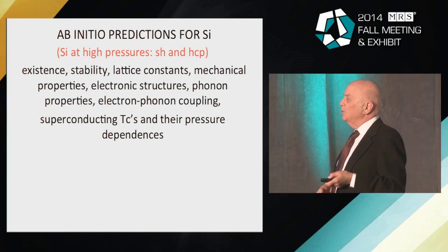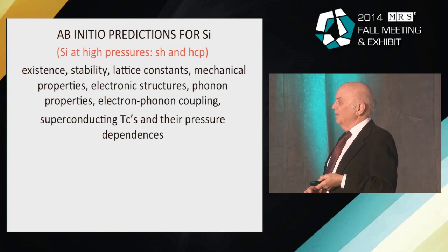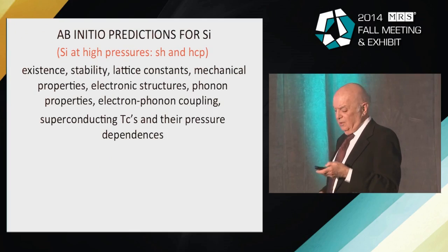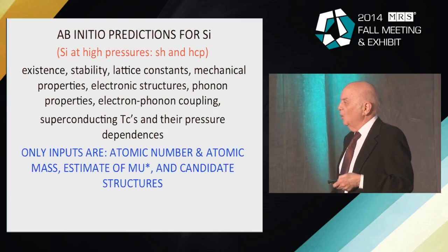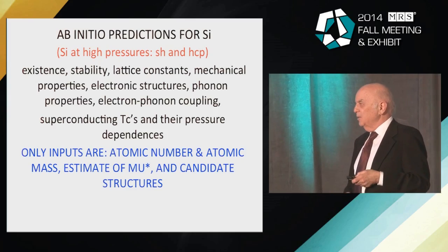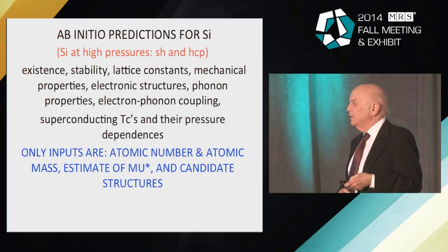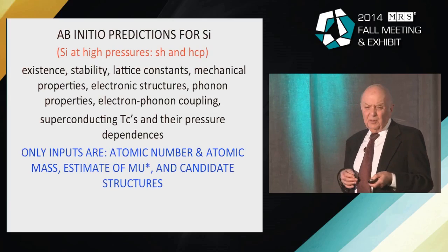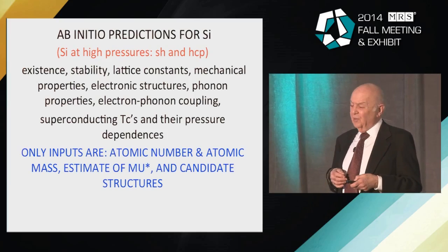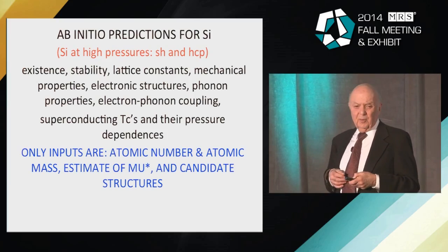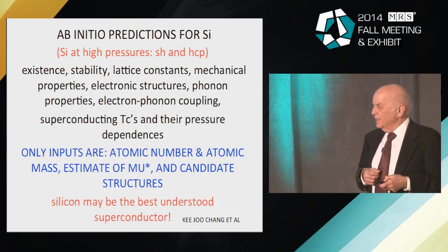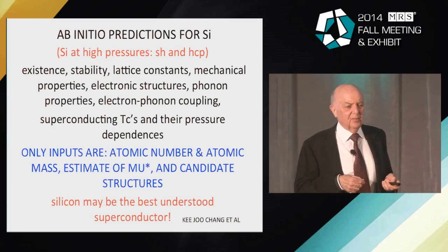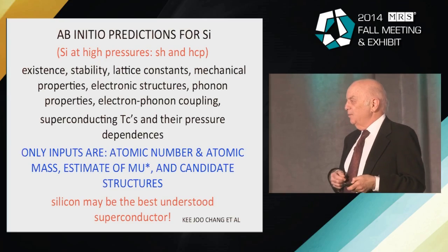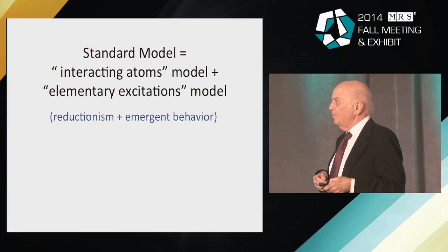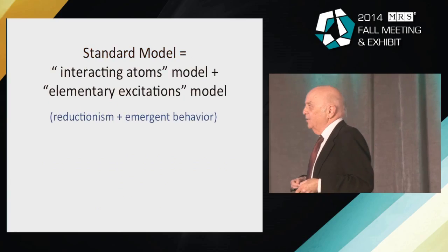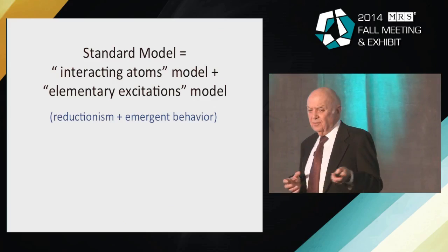the phonon, that's the vibrational properties, how the electrons interact with the phonons, the superconducting transition temperatures and their temperature dependencies. And the only inputs are the atomic number, the atomic mass, and an estimate of the Coulomb interaction, and the candidate structures. And these materials were discovered, all the properties were correct, and they were found to be superconducting at the proper temperatures. And so in some sense, silicon, which is our prototype semiconductor, at high pressures may be the best understood superconductor.